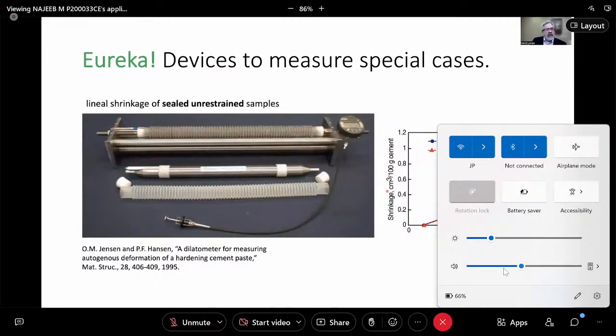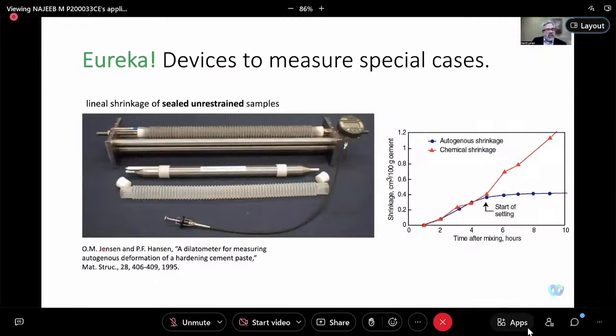Another eureka kind of moment was a test developed by Ole Jensen, a dilatometer for measuring autogenous deformation of hardening cement paste. One thing that's really hard about cement paste is that it's basically a very weak material in those early hours. How do you measure anything about that material? So he came up with this idea of having a collapsible, accordion-like form that could be filled with the cement paste. And then you have a regular length measurement of that form. And it turned out to be really effective for measuring the volume change of that early age cement paste.